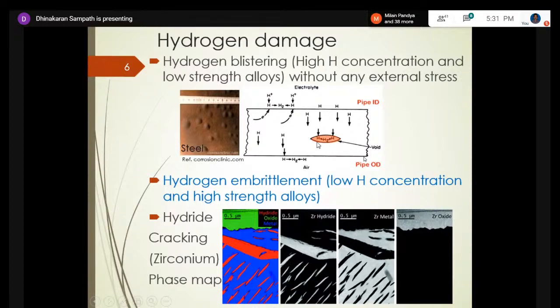The hydrogen accumulates, and it creates a huge pressure, which exceeds the yield strength of the material. At that point, it leads to bulging or blistering. So blistering later on will become a crack, and then become a catastrophic failure. And today's topic, hydrogen embrittlement, happens in high strength alloys at low concentration.